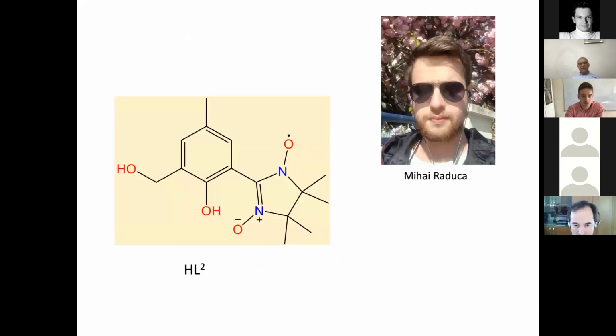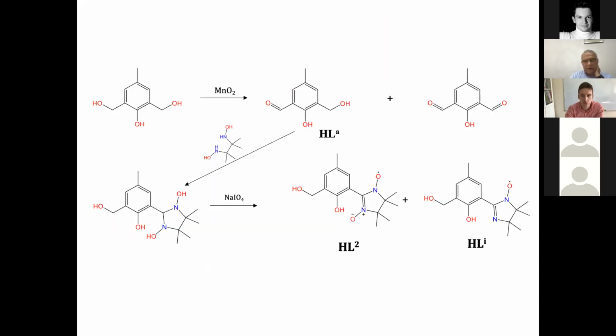So the second ligand was synthesized by my PhD student Mihai Răducă, the first one by Cristian Spânu. And this starts from a well-known precursor in designing, again, compartmental ligands. So the controlled oxidation of this dialcohol leads to the monoaldehyde. This can be separated by chromatography. And then following the classical synthetic Ullmann procedure, we obtain this ligand that has to be blue, and the iminonitroxide that generally is red.